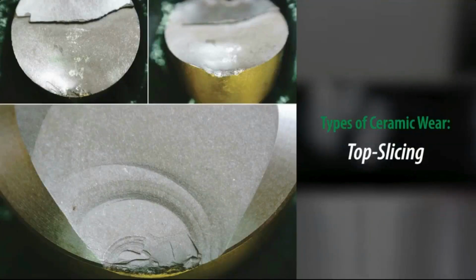Here you can see an example of top slicing. This occurs when the mechanical stresses parallel to the surface of the tool exceed the transverse rupture strength of the cutting tool. This is generally a result of excessive chip thickness combined with speed that is too low or too high. Reevaluate the cutting path to rule out any sudden increase in chip thickness and reduce cutting conditions, particularly the feed rate.